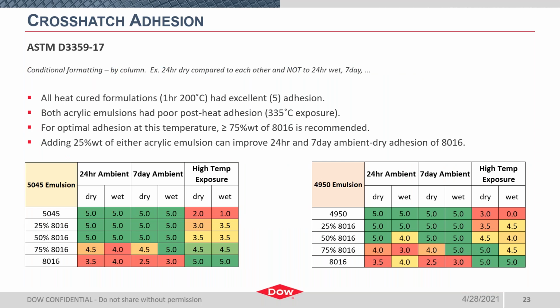For adhesion data, we collected this according to ASTM D3359-17. And to simplify the charts, I left off our heat cured data as all of the heat cured formulations showed excellent adhesion. The tables here show 2 acrylic emulsions in the top row, the left table being main coat 5045 emulsion, and the right table is the data for main coat 4950 emulsion. From there, as you move down, you increase the level of silicone content. So each table shows the same 25, 50, and 75% silicone modified of that respective acrylic before displaying on the bottom row the all silicone formulation or 8016 performance without acrylic.